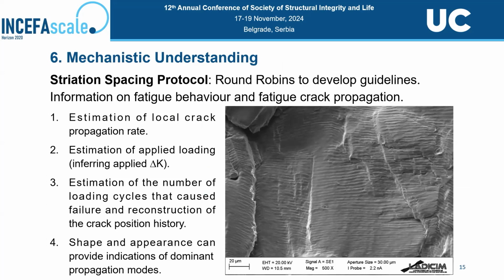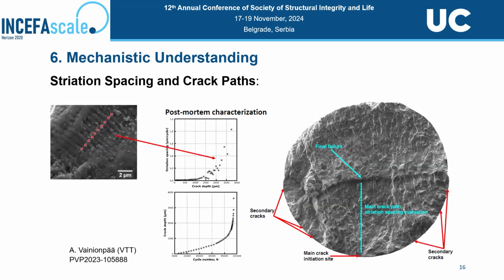Another important topic that we are performing is this analysis of mechanistic understanding by analyzing the fracture surface. So what information are we going to obtain from this analysis? Estimation of local propagation rate, estimation of applied loading and the environmental factor, estimation of the number of loading cycles that cause the failure, and reconstruction of the crack position history. And the shape and appearance can provide an indication of the dominant propagation. Well, this is an example of one specimen that has this crack path propagation in the middle of the specimen, and all these crack growth rates that we can find along the cross section.